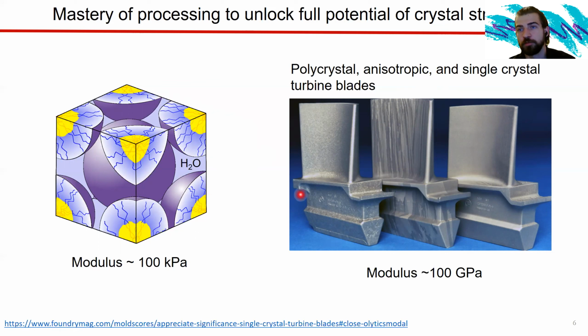Now, a modern turbine blade, we can actually make into a complete single crystal. So over here, this blade is one crystal, and as a consequence of this transition, we have a huge increase in efficiency, which has driven advancements in everything from airplanes to power generation, and that's a huge deal. So with soft material, the modulus is a lot lower, right? Orders of magnitude lower. And so we have different processabilities other than extreme thermal annealing procedures, where we can shear them, we can make them into a nice layer, and this will affect our crystal structure.